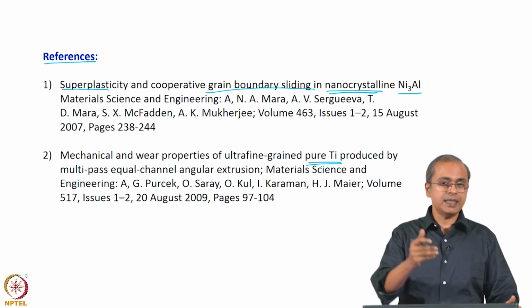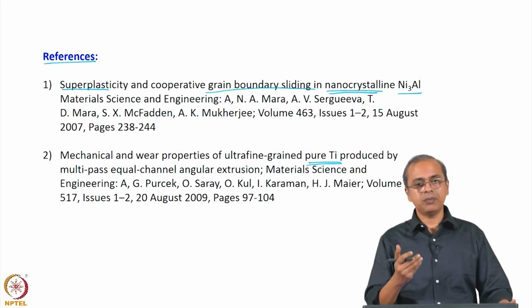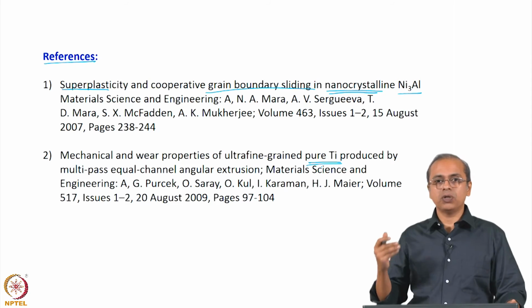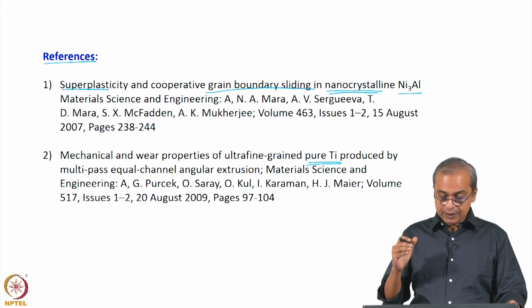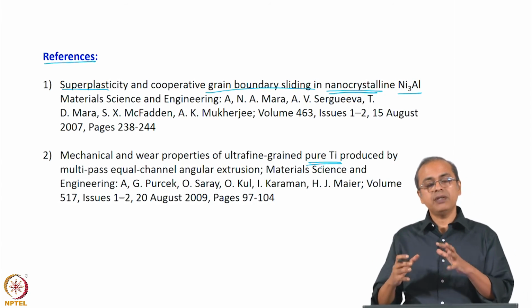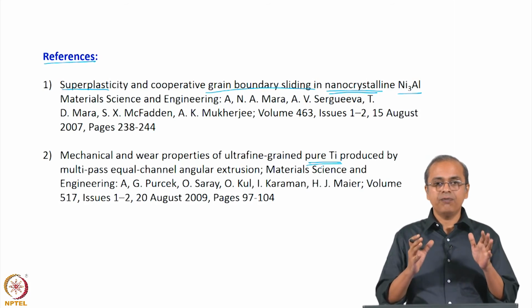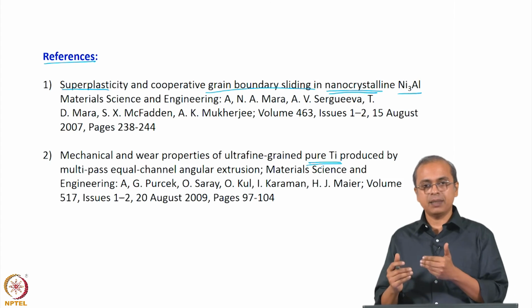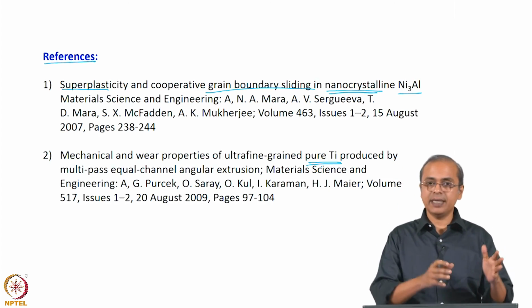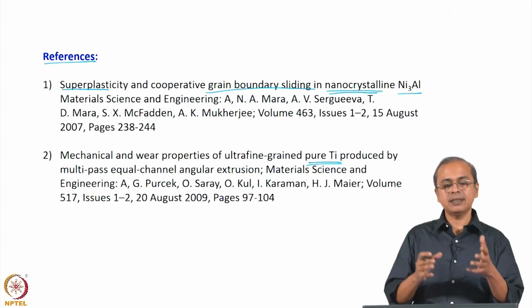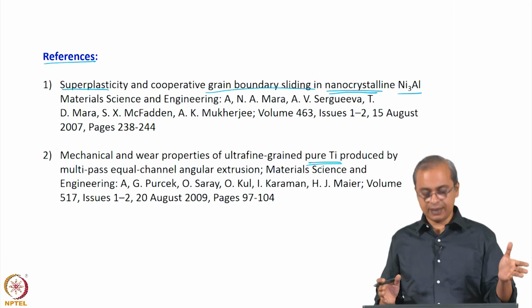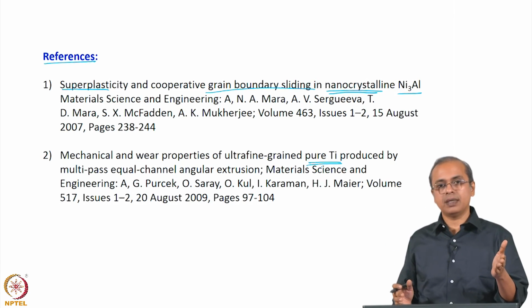So, if eventually they start leaching out of the titanium, it is not good for our body. So, their focus was to see if you can actually make titanium mechanically suitable for applications inside the body by improving its mechanical strength as well as its wear properties by simply going to an ultra fine grained structure, which again means nanoscale structure.